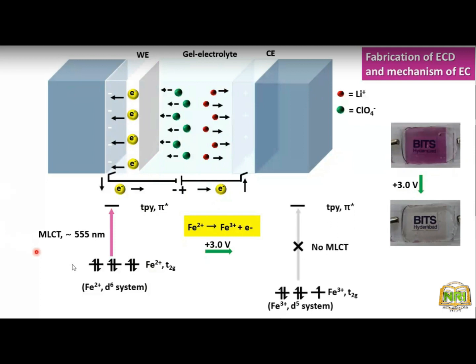Because when iron 2 plus becomes iron 3 plus, we know the d-d splitting, t2g and eg. Suppose here t2g is there, here eg is there. When iron 2 becomes iron 3, this t2g and eg gap separation becomes high, so the Fe3 plus t2g level would be down. Now from this t2g level to pi star, the transition won't fall in the visible region. It will go to the UV region. That's why we cannot see the color, and that's why the film becomes colorless.